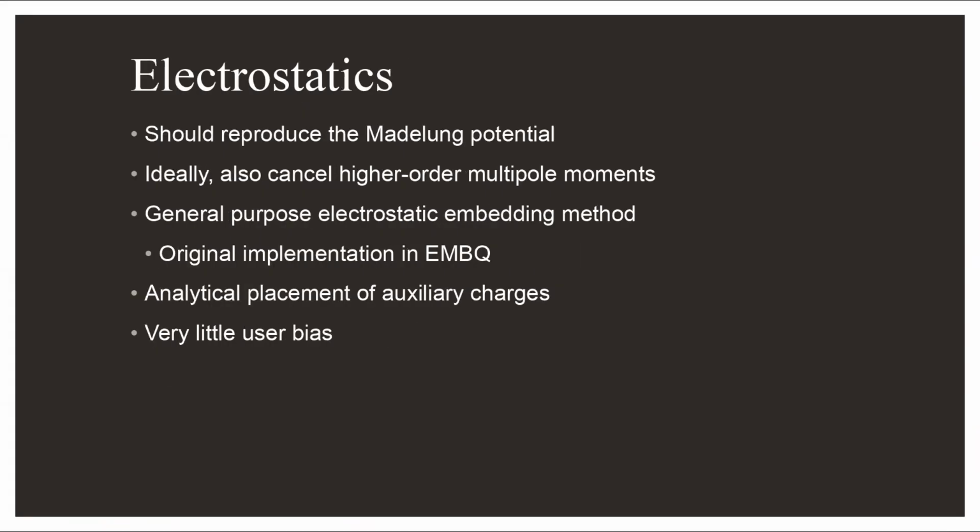Okay, so electrostatics. If you have an ionic crystal, electrostatics is important, and you really want to have the potential from the crystalline field well represented. And ideally, you should also try to cancel as many higher order multipole moments as possible over your entire structure, because they can introduce some spurious errors. If you're just interested in energies, dipoles are probably fine, but if you're interested in some other properties, higher order might be necessary.